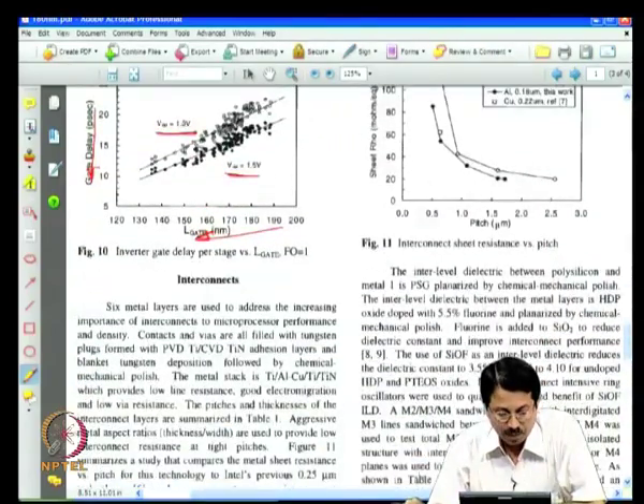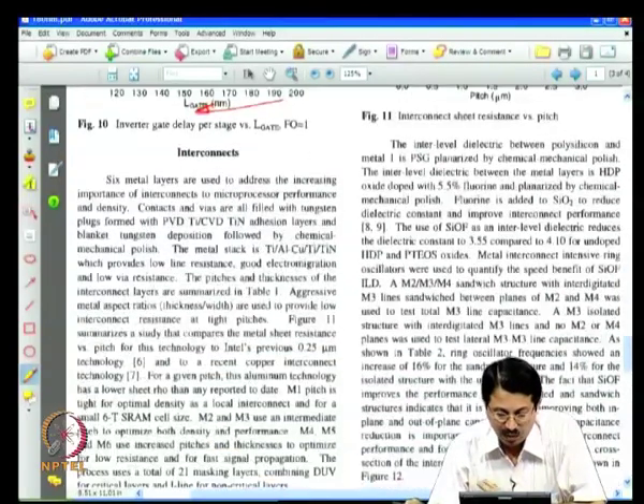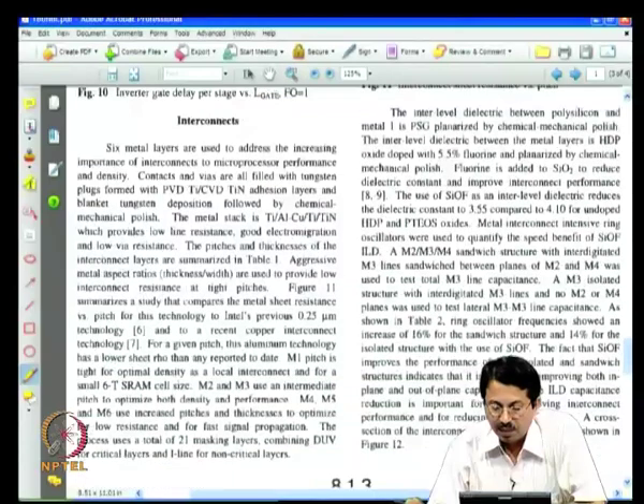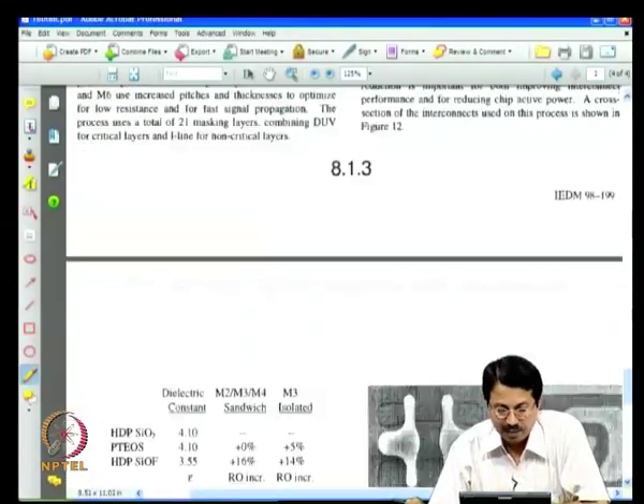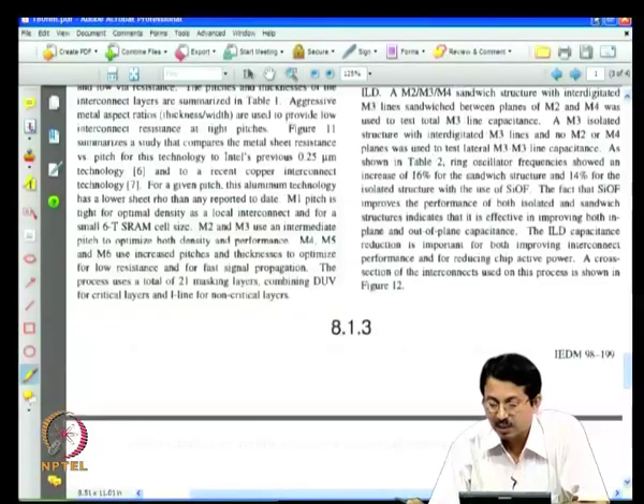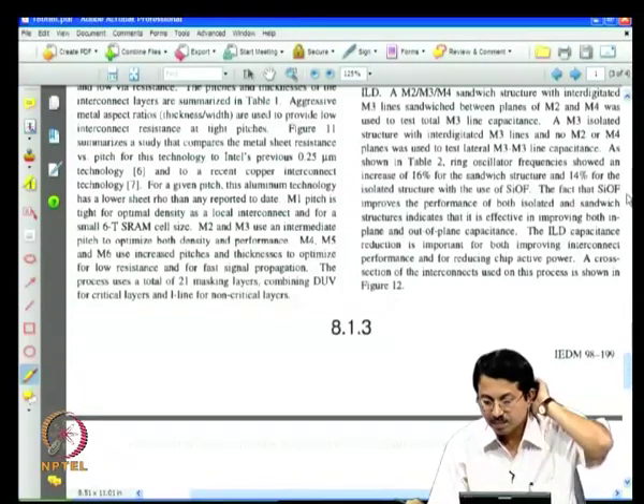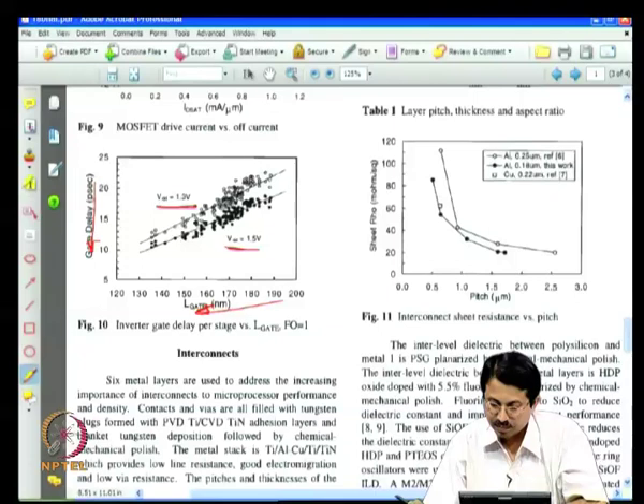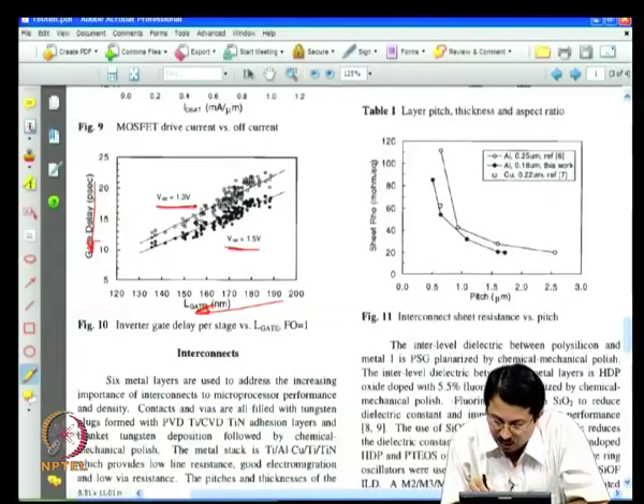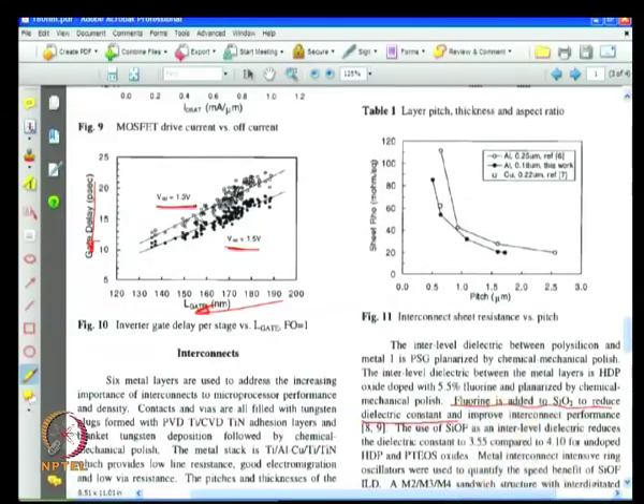And they do the interconnects, interconnect is essentially aluminum in this case, they have not yet used copper, but the only thing that they have done different in interconnects is to use fluorinated silicon oxide, as I mentioned earlier here. You see, fluorine is added to a silicon oxide to reduce dielectric constant and improve interconnect performance. The use of SiOF as an interlevel dielectric reduces the dielectric constant to 3.55 compared to 4.1 for undoped silicon oxide. Remember, silicon oxide, the dielectric constant is around 4.1, whereas that comes down to 3.55.